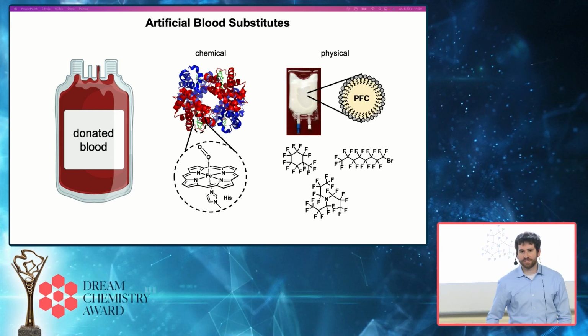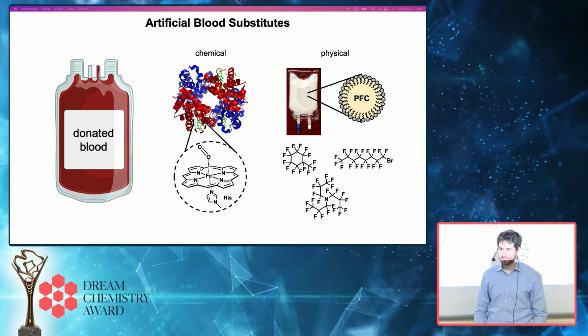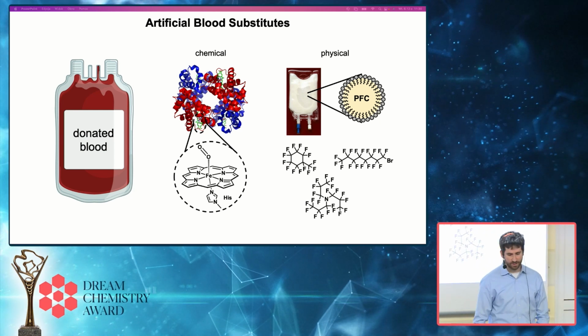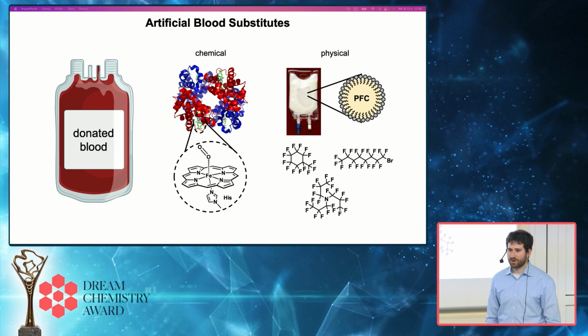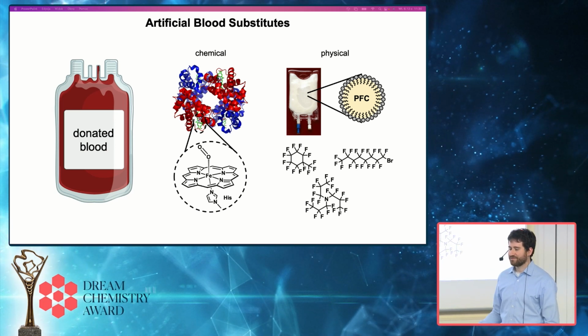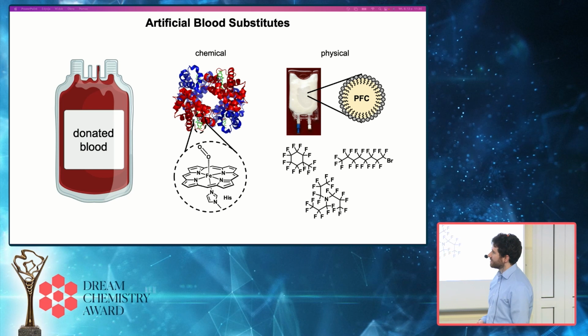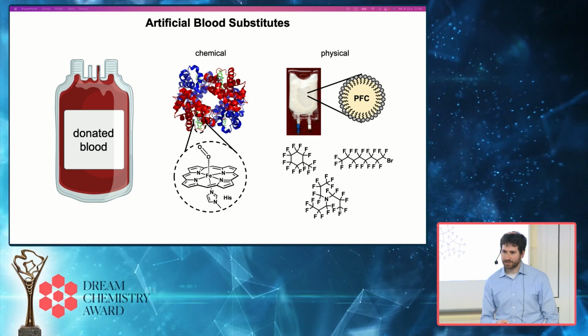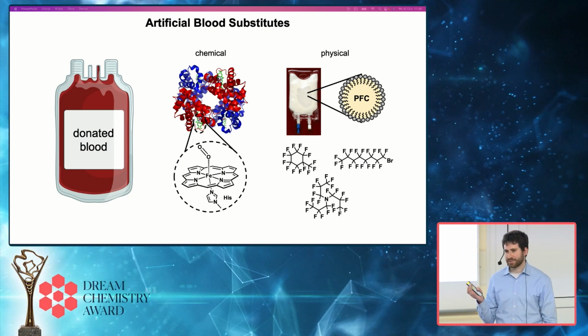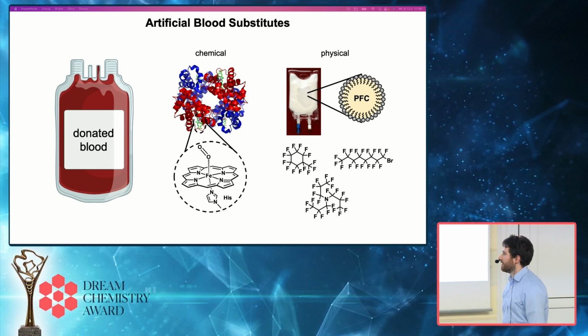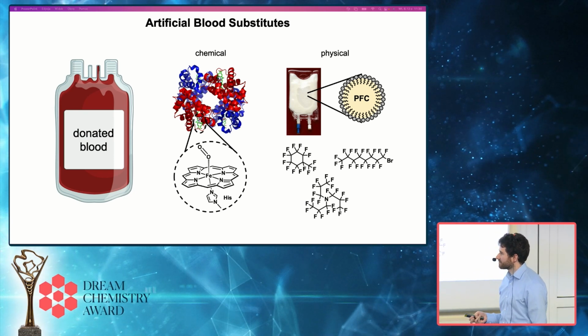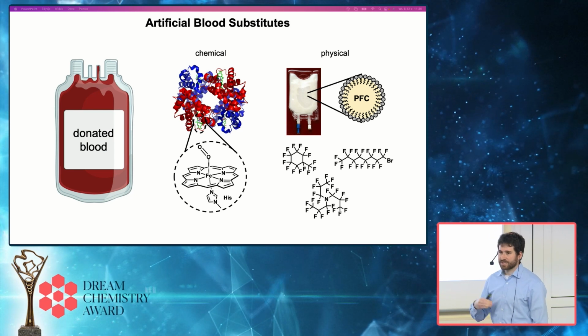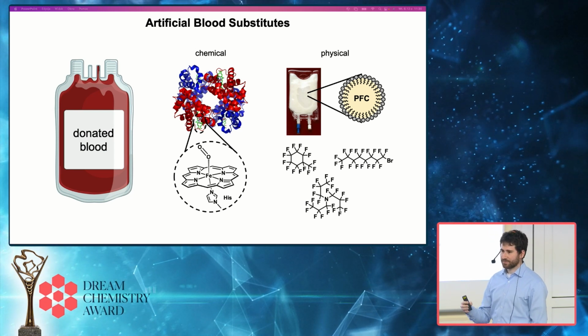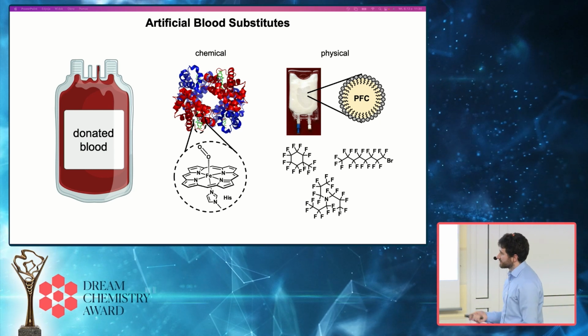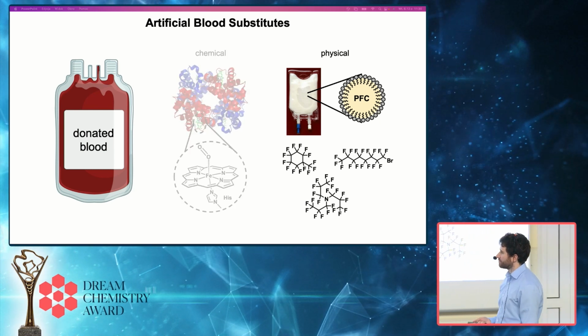The other approach that people have looked at is to take high oxygen solubility solvents, things like perfluorocarbon liquids, which I'll talk a bit more about in a second, make them into emulsions in water and transport oxygen by physically dissolving it at high densities. So here, these are solvents, liquids that can absorb much higher quantities of oxygen than water. These basically increase the density of oxygen through physical dissolution rather than a chemical binding mechanism of oxygen. So these have actually had the most success clinically, so I'll just describe a little bit more what's going on in some of these solutions.